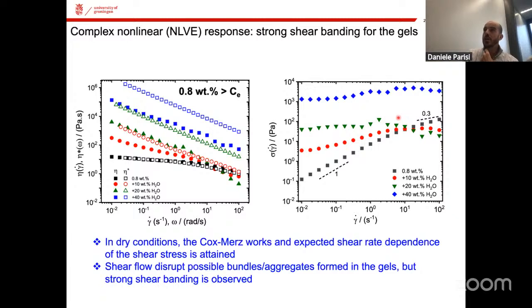And this is a very known flow instability called shear banding. So meaning that there are different bands in the fluid, if you want, along the velocity gradient, where there are layers of fluid moving faster but with a lower viscosity, and other layers moving slower and with a high viscosity.